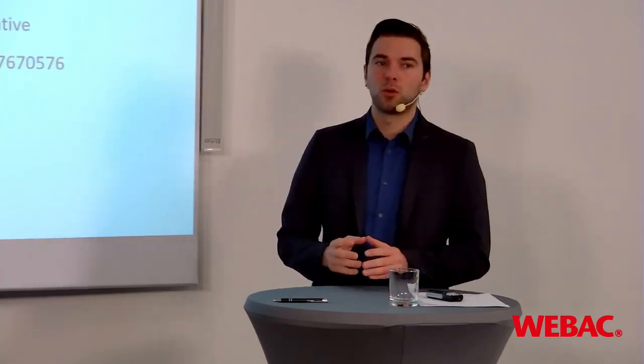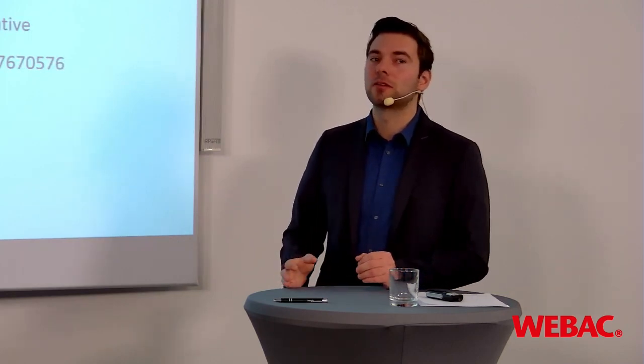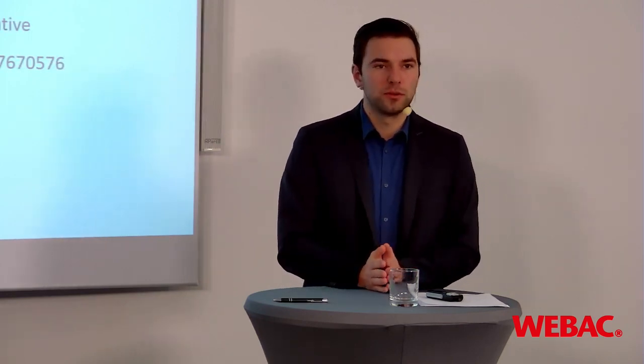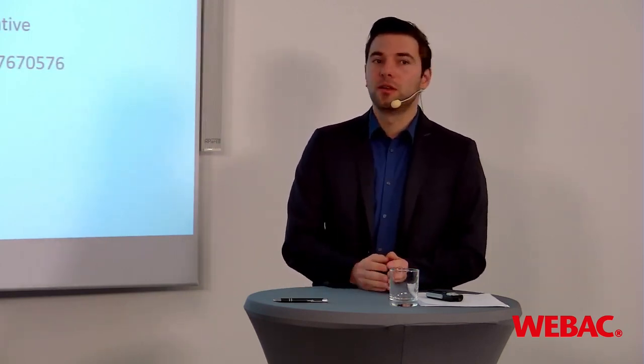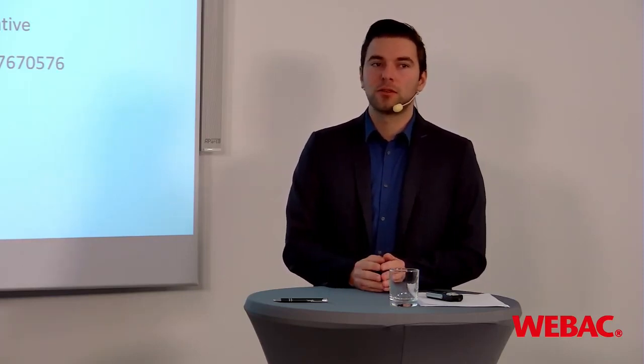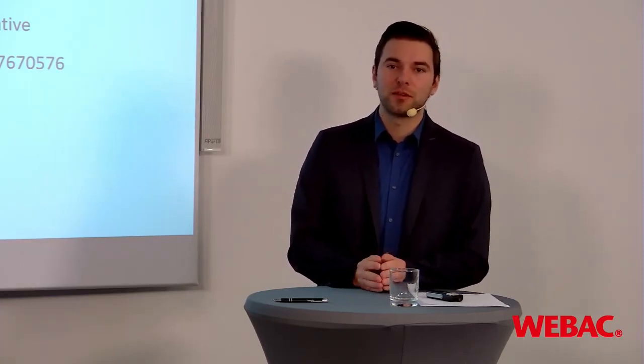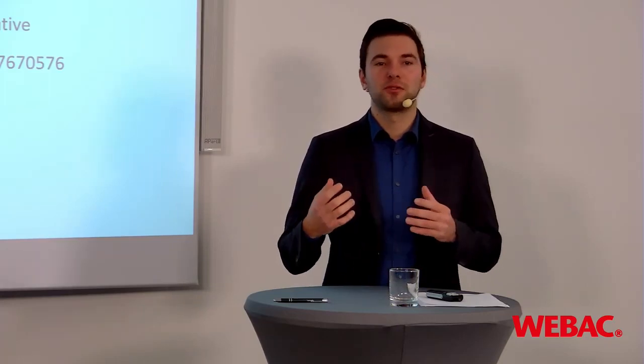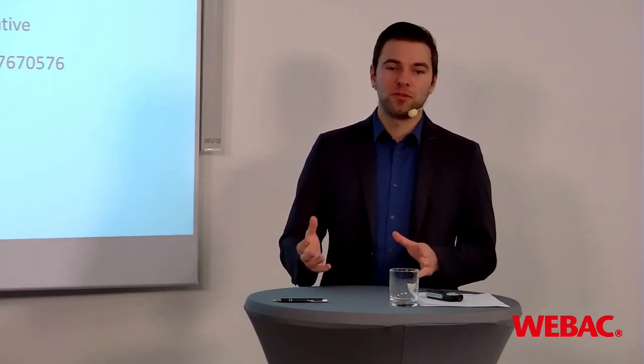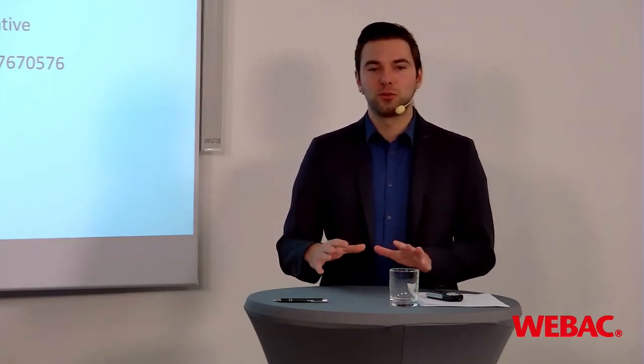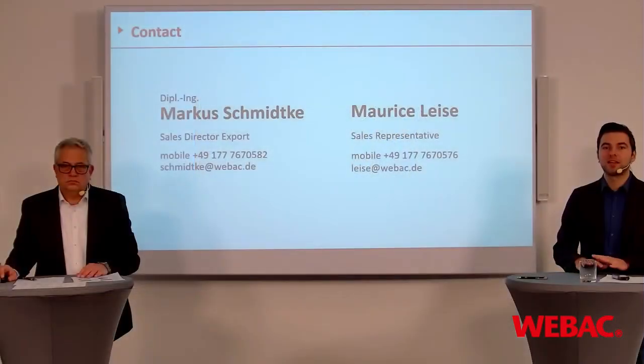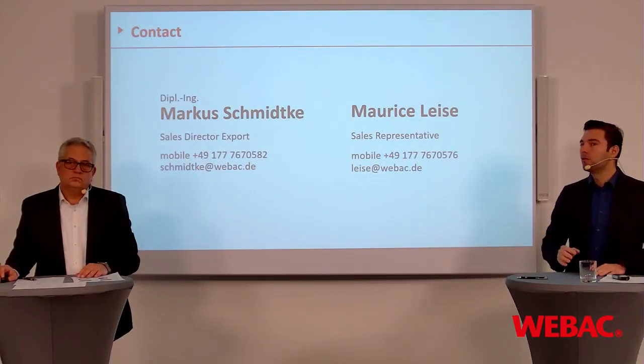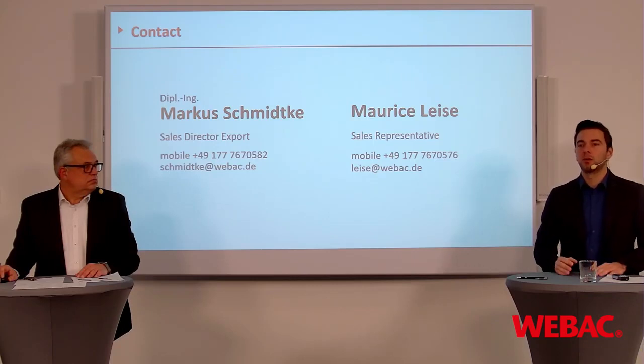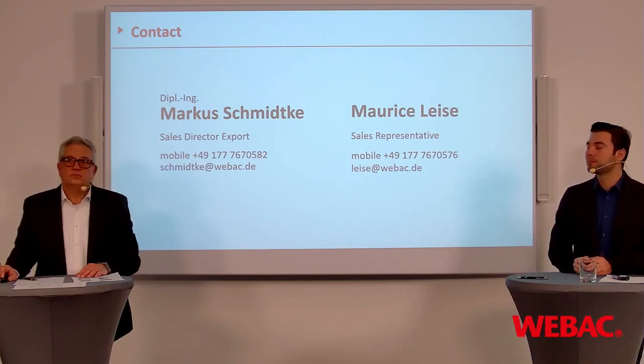Another case where we always recommend to use the patching is for a force transmitting filling if we are working with epoxies, because there it's very important to achieve a high filling rate. And according to the standard here in Europe, you need to achieve a filling rate of at least 95% to have a successful injection, and therefore just to prevent that the material is coming out too easily or that the material stays inside your construction, for a force transmitting filling, we always recommend to use the patching.